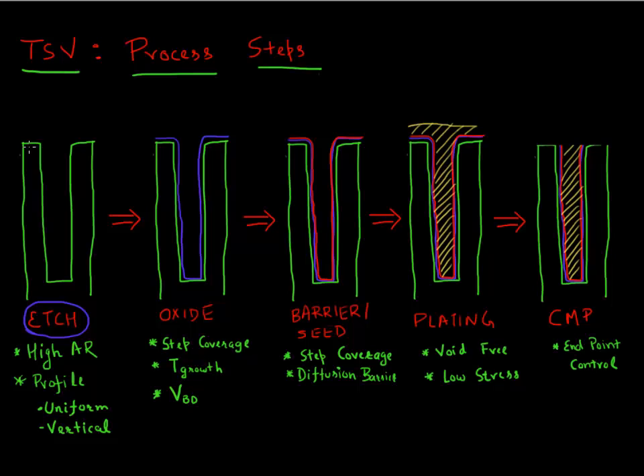One of the critical features of this etch is that it's very high aspect ratio. So typically this would be anywhere from 100 to 150 micron deep, and it would not be more than a few micrometer wide. So it would be from one to five micrometer wide. You could have it more wider, but then what you'll compromise is your layout efficiency. So if you make it wider, you need a much larger area for each of your TSVs. So you want to keep this TSV width small.